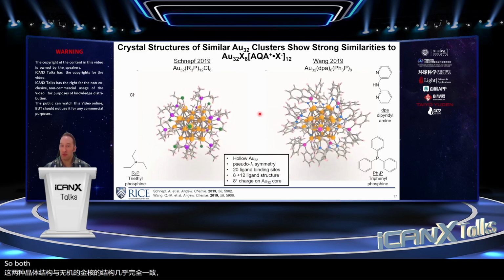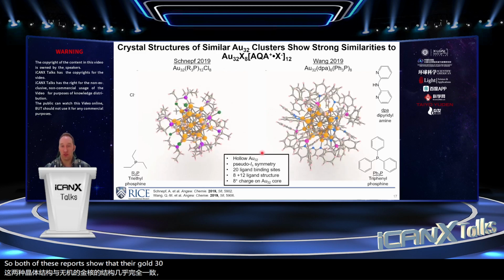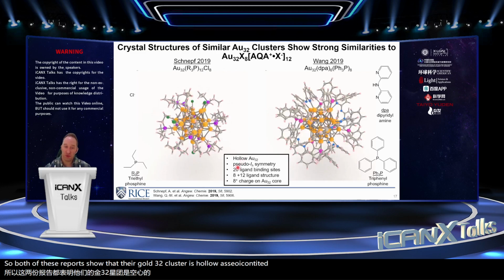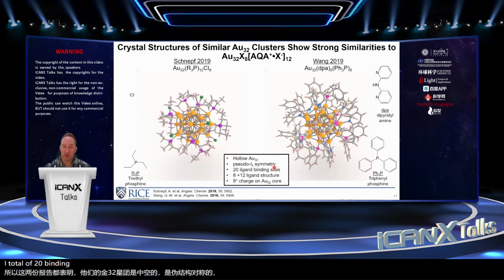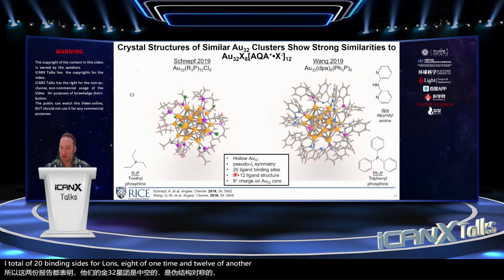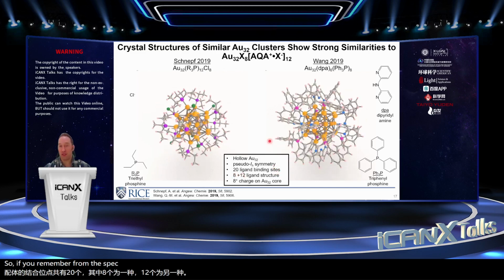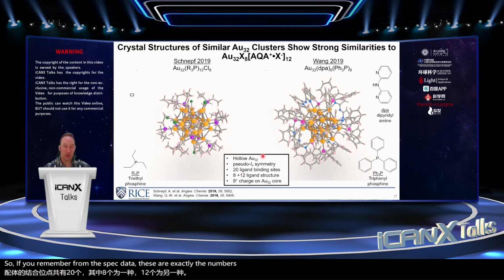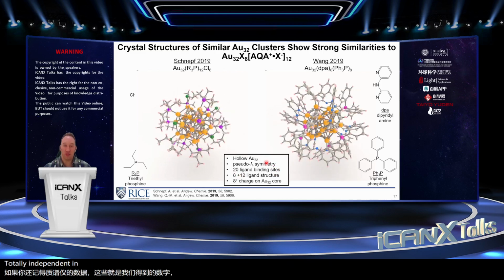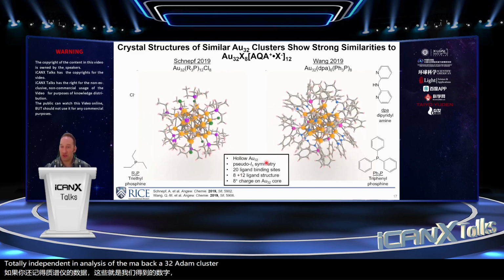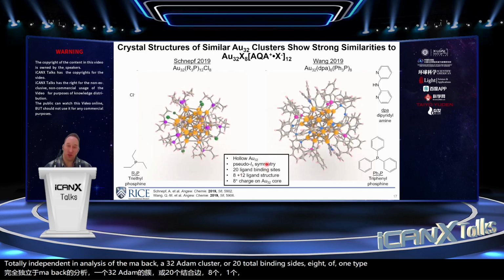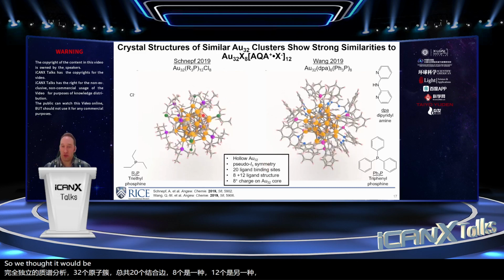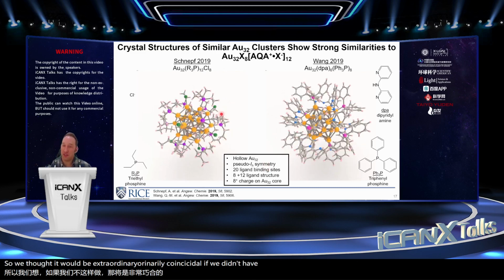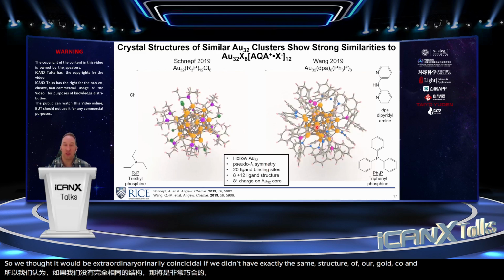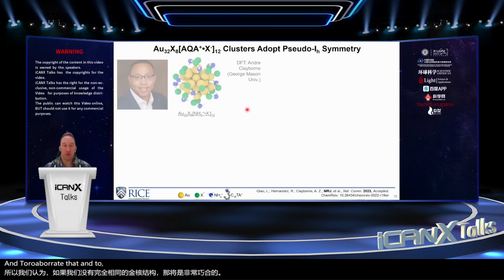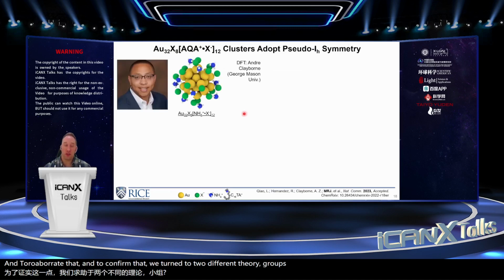So both of these reports show that their gold-32 cluster is hollow, has pseudo-icosahedral symmetry, a total of 20 binding sites for ligands, 8 of one type and 12 of another. So if you remember from the mass spec data, these are exactly the numbers that we got from our totally independent analysis of the mass spec. A 32 atom cluster, 20 total binding sites, 8 of one type, 12 of another. So we thought it would be extraordinarily coincidental if we didn't have exactly the same structure of our gold core in our case. And to corroborate and confirm that, we turned to two different theory groups to help us look at this problem.